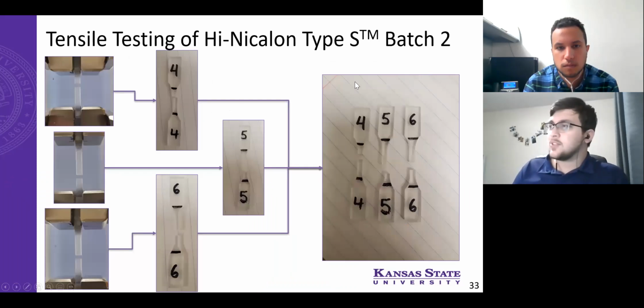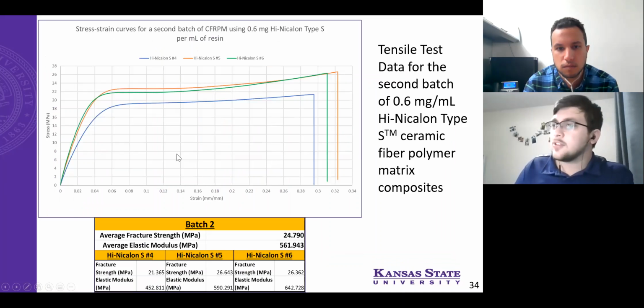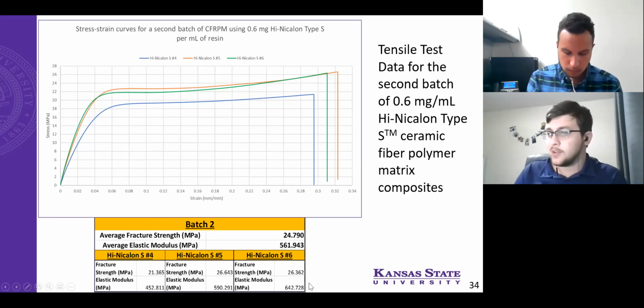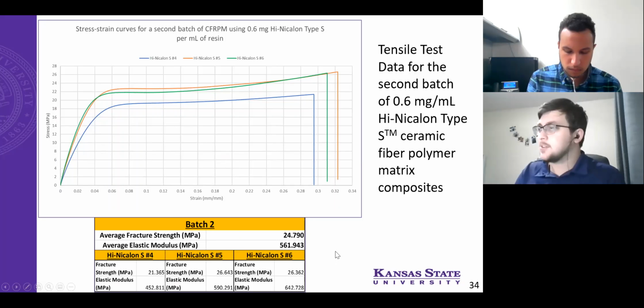So this is batch 2, which was the same tow, but with more consistent fiber length. You can see during, after, individually, and then against each other, showing how they broke in different places again. And then here's the stress strain curve and tensile test data from that. Batch 2 actually seemed to, with the exception of number 4, which is just the first sample that I tested from this batch, which seemed to underperform compared to the other 2, but did have a higher average elastic modulus, though not necessarily consistent across this batch with 452, 590, and 642 megapascals each.